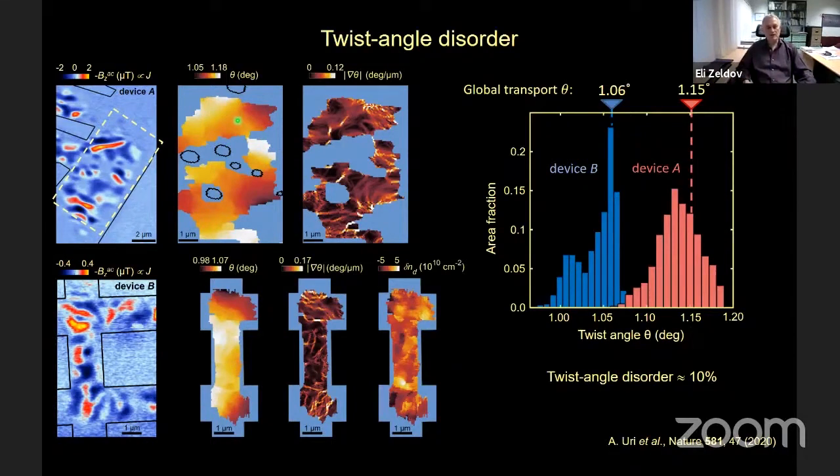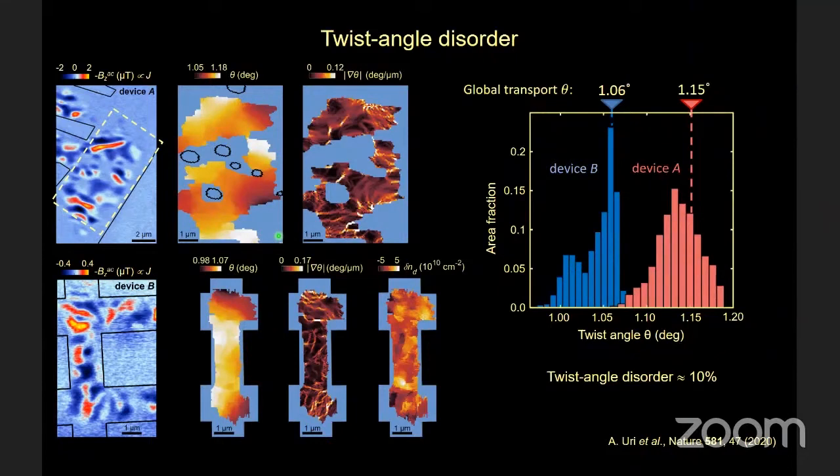So as long as strain does not change the area of the unit cell, it will be invisible to us. What is visible to us is variations in the unit cell area. So that's essentially the map of the unit cell area, or the square root of this. This is actually a map of the square root of the unit cell area. Is it clear? Yes, thank you.